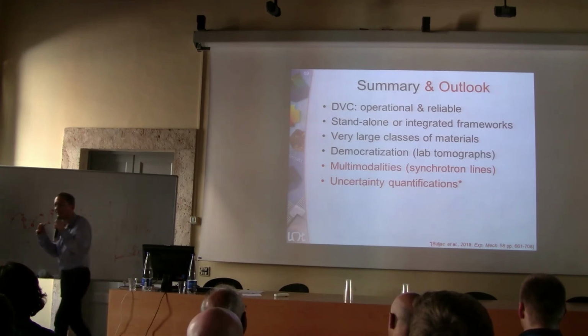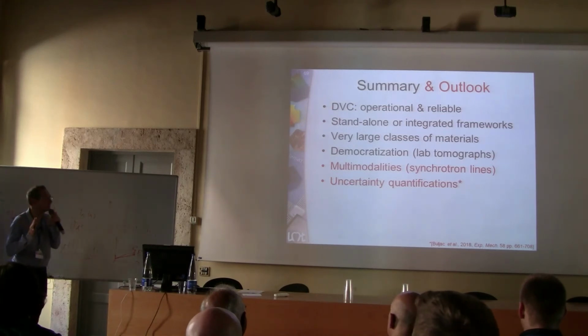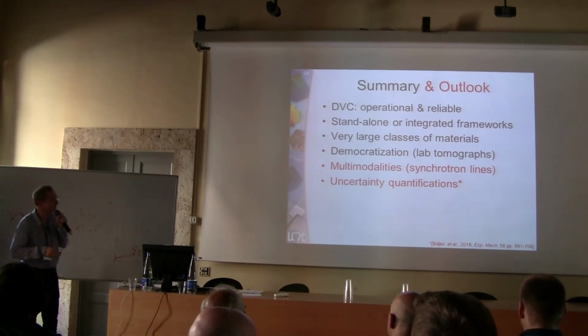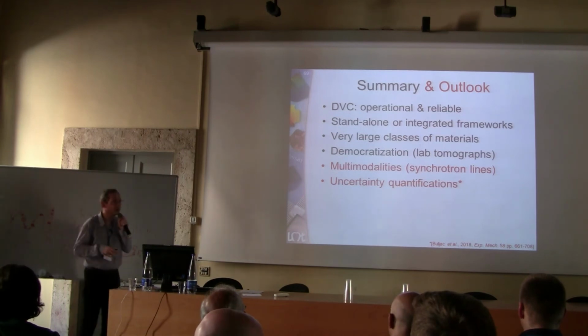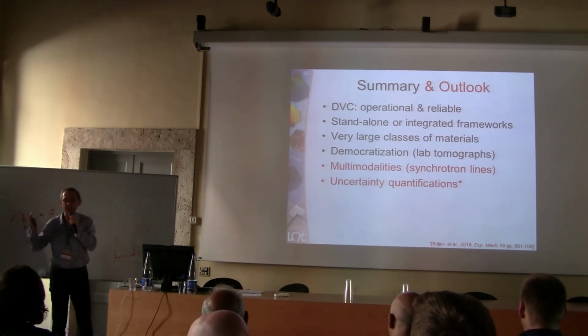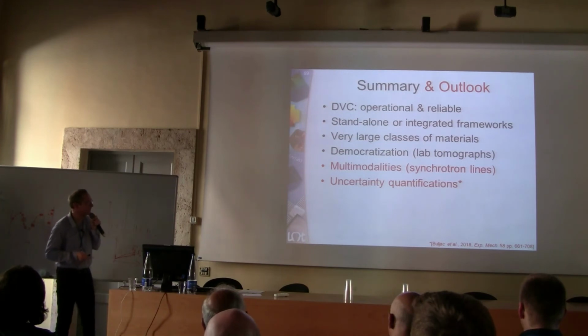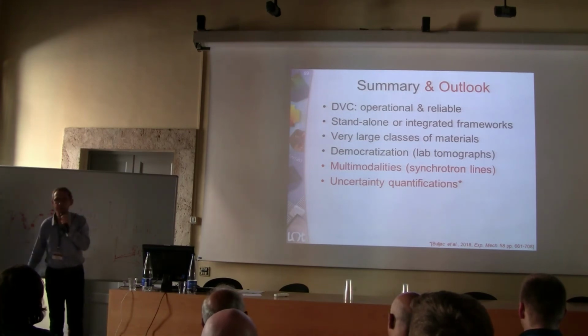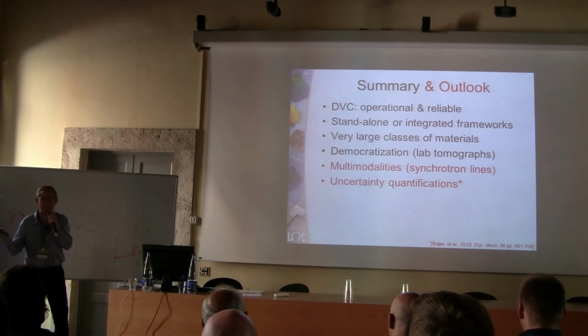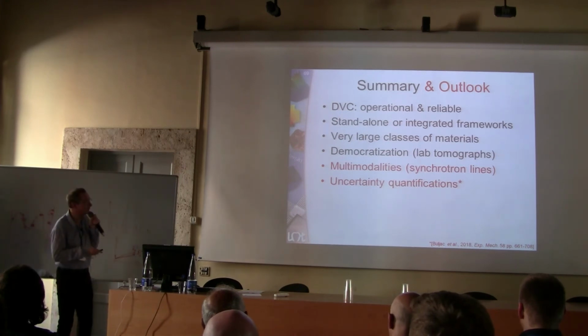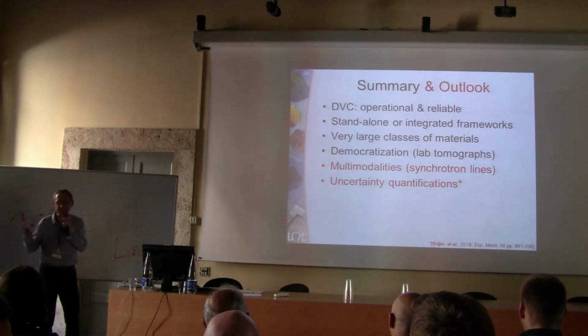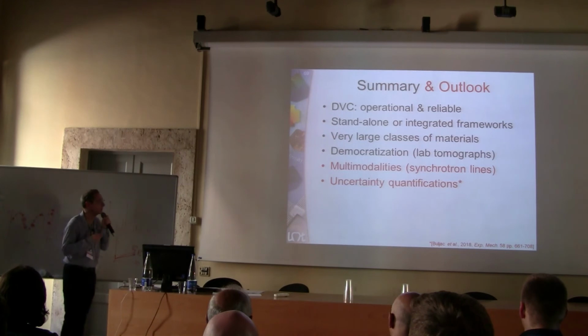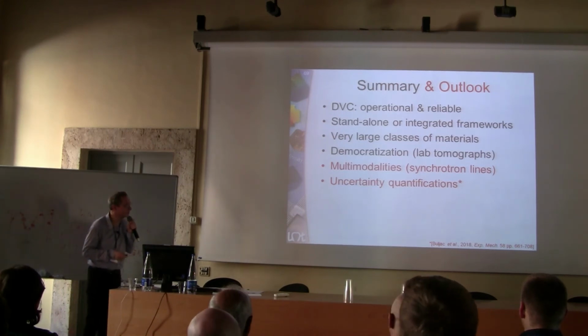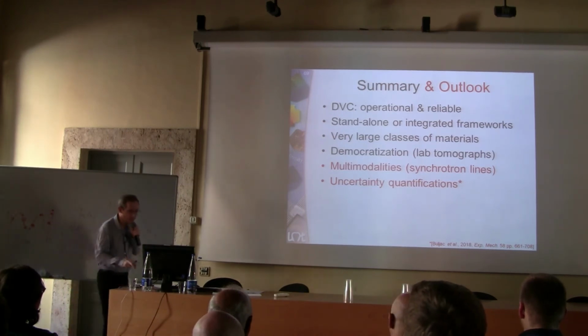I just mentioned that at a given point, what is really critical in these techniques is to perform uncertainty quantifications. They are clearly higher than what we know in classical DIC techniques, but not too high, which means we can still get meaningful data from these analyses. But clearly, that means you have to be cautious and perform these uncertainty quantifications on a regular basis.